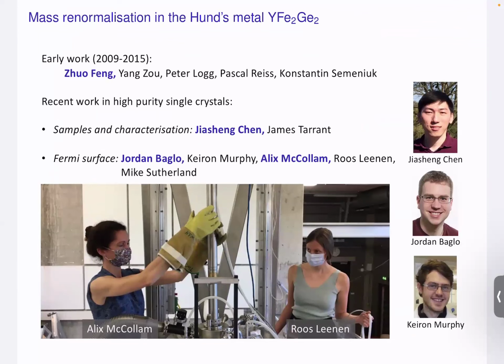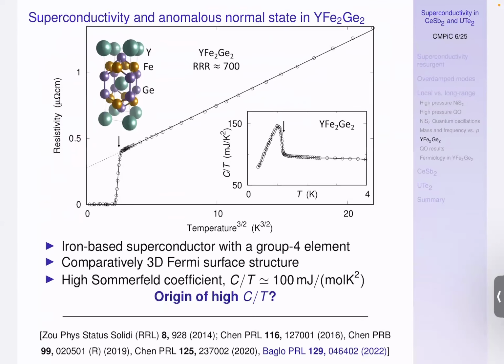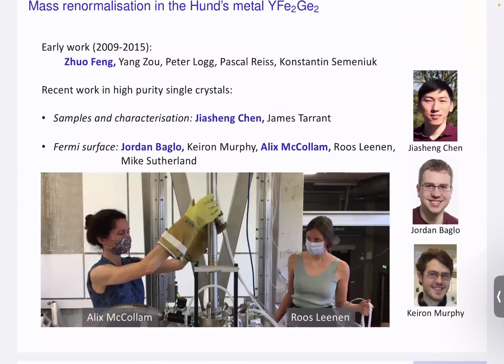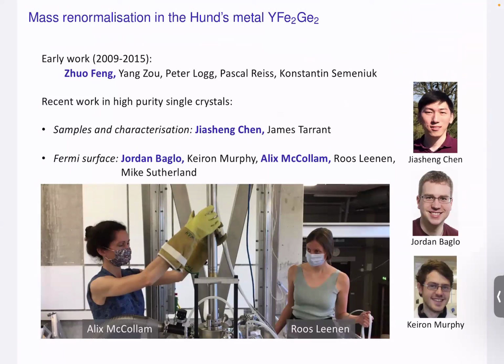And here's another example of this idea when we worked on yttrium iron 2 germanium 2 quite a lot in my group. We should be a bit more respectful to all the people who did the work. So again, over the years, a lot of PhD students have worked on this. In particular, the main breakthrough came when Chen, still in Cambridge now, but maybe not much longer, was able to produce really high quality crystals, resistance ratios of 700. And this shows Alix McCollam, Roos Leenen, doing high field measurements on it in Nijmegen. But most of the Fermi surface studies actually were done by Jordan and PhD student Keiron here in Cambridge.